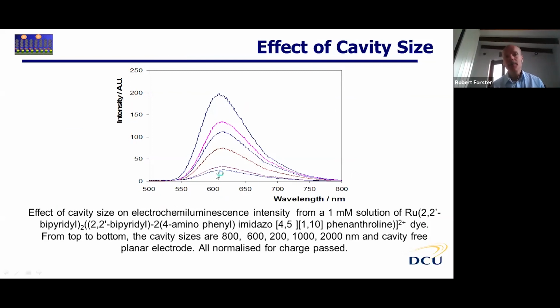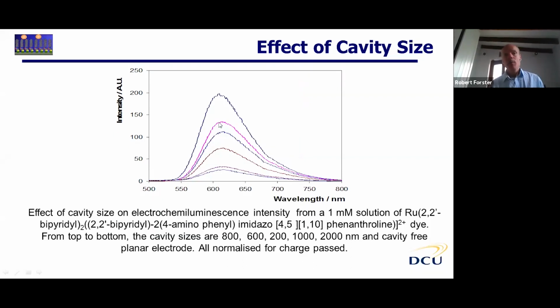And now you see something that's interesting. If you take the planar surface, you get a certain intensity of light. If you array 2000 nanometer cavities, you get a brighter emission; 1000 brighter still; 200 a brighter still. And then when we go to 600, you get an even brighter emission, but the optimum cavity size is about 800 nanometers. So there's an interesting message in terms of size.